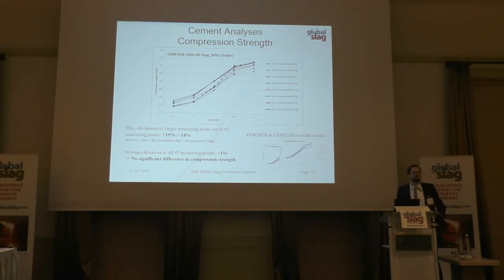So we have done many mixtures of dry granulate with clinker and also wet granulate with clinker to compare each other. We have done a mixture with the CEM II/A cement, the CEM II/B cement, with different ratios and contents of dry granulate or wet granulate in the product, and also cement mixtures with different fineness of the product. Summing up all results of the compression strength, we have seen no significant difference between wet granulated slag and dry granulated slag. Summing up all 45 measuring points that we put together, the difference is nearly 0%.